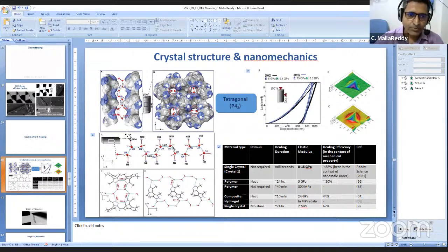Now this is a different, perpendicular axis. This is a long axis now, and when you break it here, this is the axis where I expect these to break. Going by the phase indexing, you see that this is parallel to this. So these are the bonds which are breaking, basically. These are the planes. It's not a very weak plane because you are cutting through strong hydrogen bonding interactions as well. But this is where you don't have covalent bonds. Of course, it's not atomically flat, but that is where you have a slip plane.